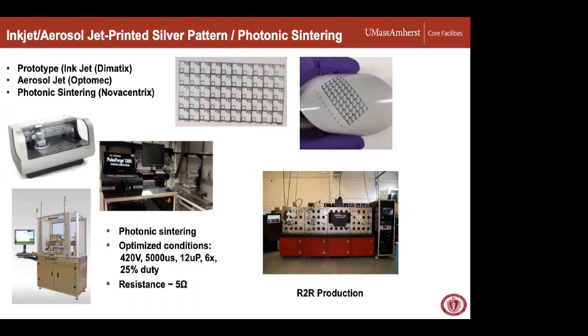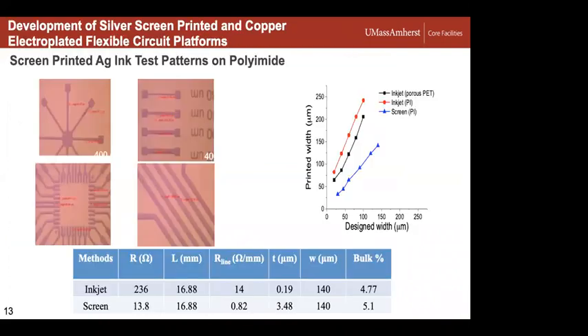And so that's where we work with both for the materials, the surface energy of the substrate, whether it's Kapton or PET, which is another form of clear plastic. And then we work with post processes, the curing temperatures, and then eventually the photonic sintering, which can further densify and improve the line resistance of these printed conductors. And so I show that tool on the bottom right. We have both that in as well as the center here, the PulseForge 1300. That's basically a standalone unit, not roll to roll. And then we do have the same thing, roll to roll.